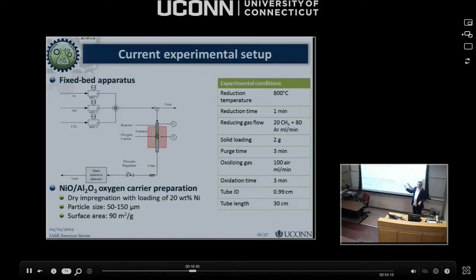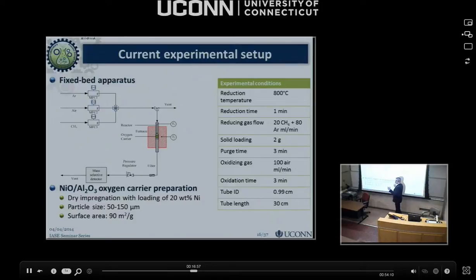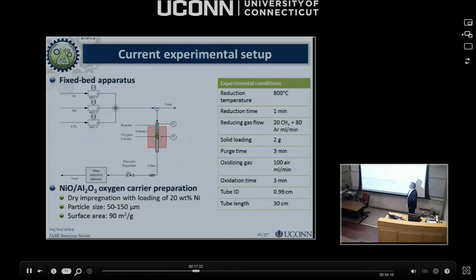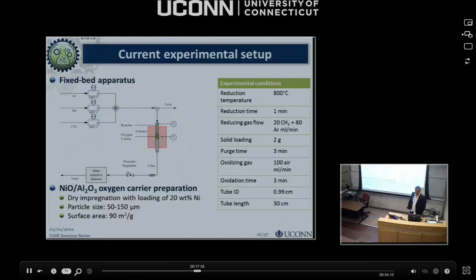When my background is all in modeling, I joined UConn and realized I had no data, so we started setting up a few reactors to verify things. This is a very standard small fixed-bed reactor for chemical looping. Instead of having two reactors in a small fixed bed, we switch the gas flow — from air to fuel and back to air — and we measure everything at the end with a mass spectrometer. We work with nickel oxide on alumina as our oxygen carrier and methane as our standard fuel, although we can do hydrocarbons. This started to focus on chemistry to verify the kinetic analysis and studies, and we're taking it a little further on the systems aspect.